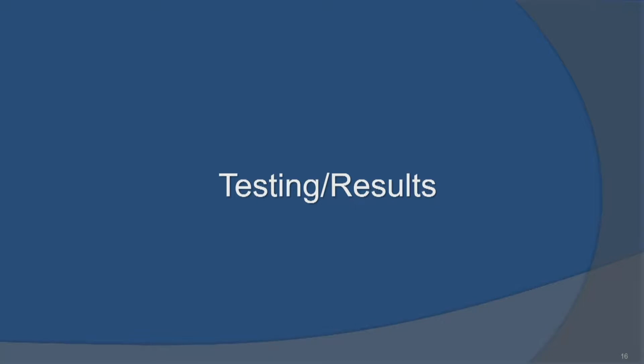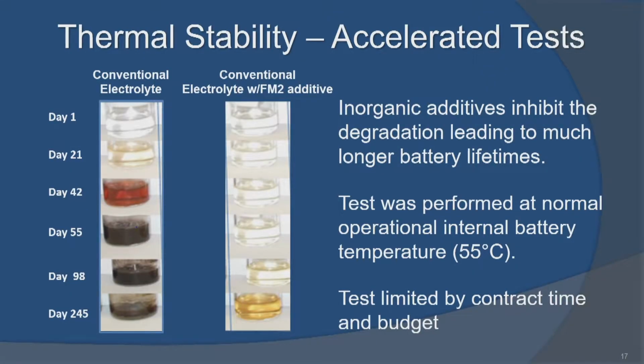So how about our testing and what are our results? First, we did accelerated thermal stability tests because what we have to do is keep the battery from getting too hot, which causes degradation of the current organic systems. As you can see on the left, under our thermal testing, very quickly, in just days, the organic electrolyte rapidly degraded, first discoloring and then turning into sort of a tar, which definitely would not leave you with a workable battery. Just by adding a few % of our new inorganic replacement, what you see is over the same time frame in a side-by-side test, by the time that the organics are completely destroyed, ours have barely even begun to discolor.